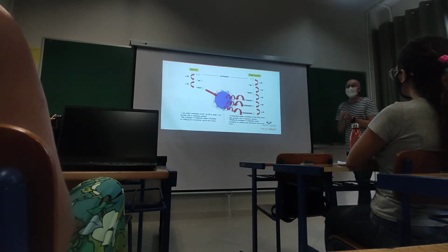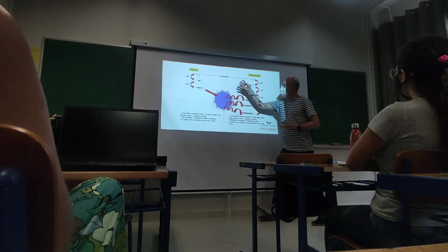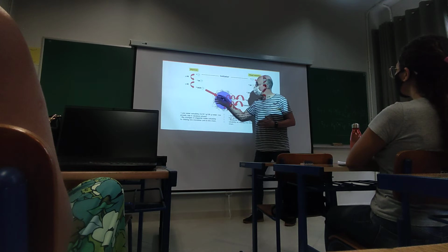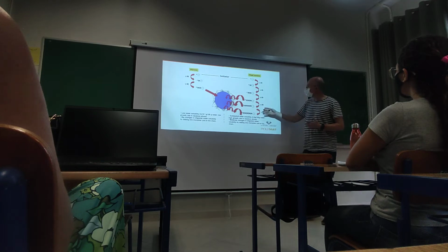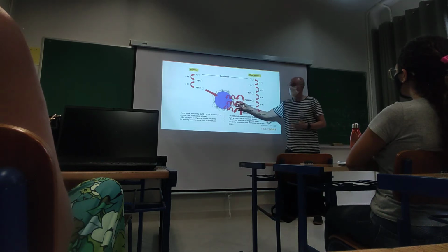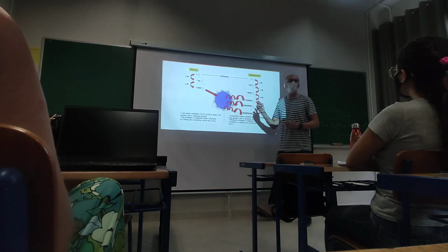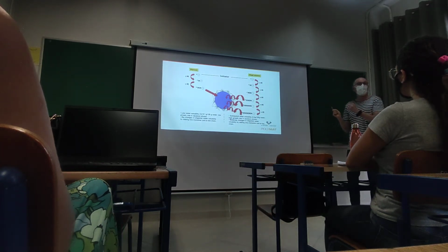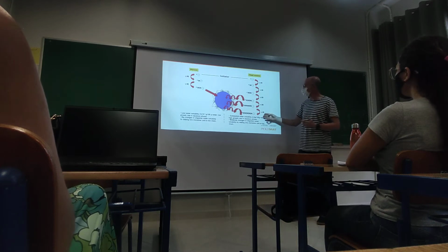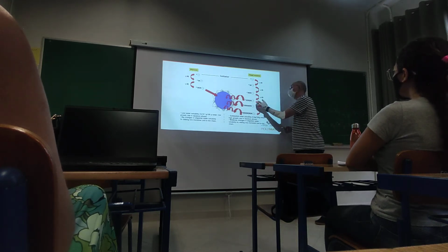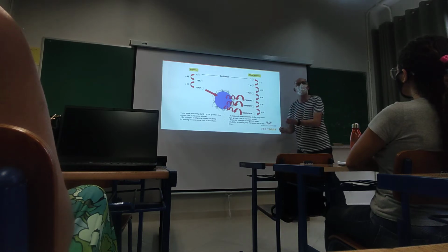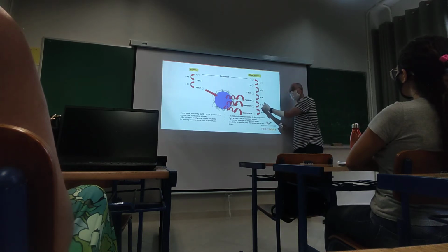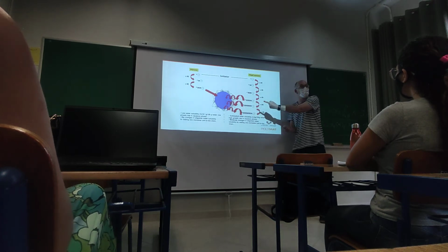So we need to add a lot of units of vinyl acetate to be able to have something which is surface active. So the conclusion is that the entry of radicals depends also on the rate of formation of the surface active radicals. Okay? So here, with styrene, in which you have 2 units, they will enter the polymer particles. Whereas with vinyl acetate, you will have plenty of sizes that can enter, but they have much more time to terminate also in the aqueous phase. So this is why when you run polymerization with vinyl acetate, you might have plenty of water-soluble material, because radicals are growing and terminating in the aqueous phase before they enter into the polymer particles.